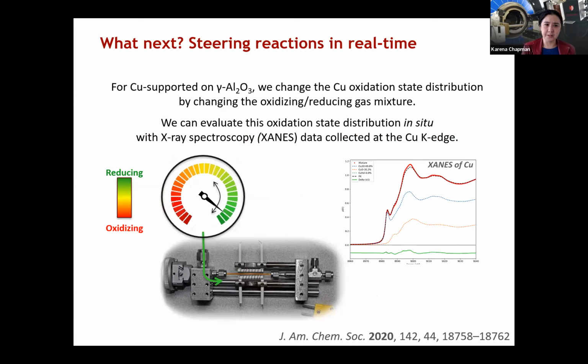The system that we chose to look at was copper supported on gamma alumina. It's very similar to that platinum example that I showed first up, where we can change the copper oxidation state by changing the gas mixture flowing over the sample, from oxidizing to reducing. And we can probe the state using XANES spectroscopy.